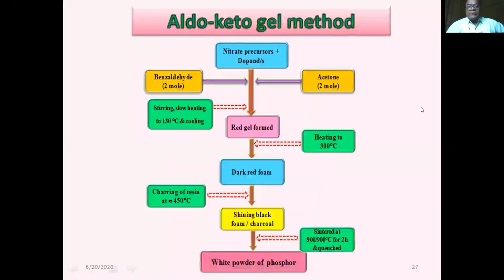Then the next method is the aldo-keto gel method. So nitrate precursors are initiated, and then benzaldehyde and acetone, then stirring, slowly heated to 130 degrees centigrade, and then cooling. A red gel is being formed. Then heating at 300 degrees centigrade, dark red foam. Then charring of the resin at 450 degrees centigrade, shining black foam and charcoal, then sintered at 800 to 900 degrees for 2 hours, quenched, and white powder is obtained.